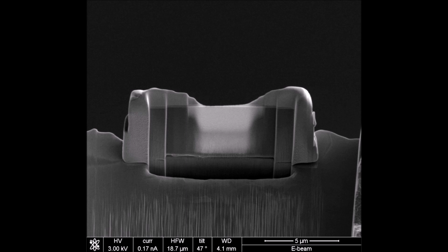And when we do that, we're typically talking about using techniques like high-resolution imaging or atomic resolution STEM imaging. And for scenarios like those, you do want a really, really thin, high-quality specimen. But that may not always be the case.